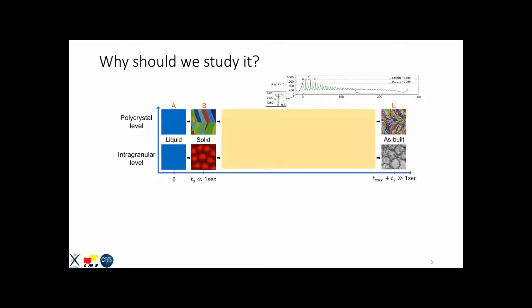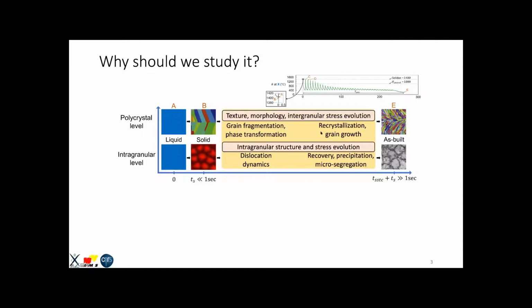So what could happen during solid state thermal cycling? Well, you could have different mechanisms that could occur. For instance, at the intragranular level, you can have dislocation dynamics, recovery, precipitation, microsegregation that could happen in the solid state. At the polycrystal level, you can see grain fragmentation, phase transformations, recrystallization, grain growth. And all of these can result in intragranular structure and stress evolution at this level, and texture, morphology and intergranular stress evolution at that level.